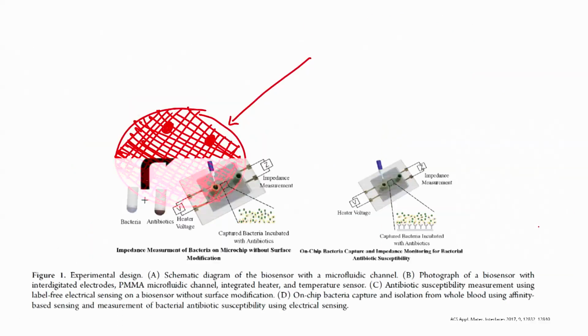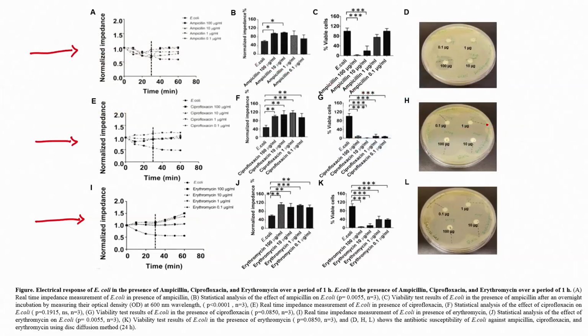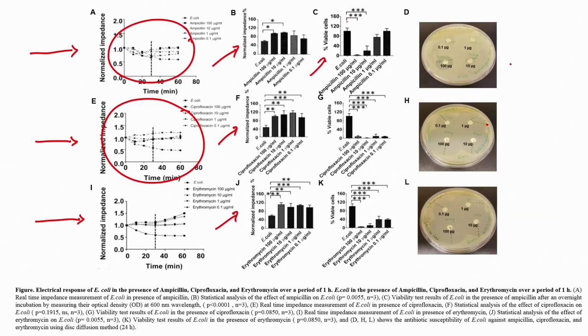antibiogram assay, correct. So, the antibiogram assay you can see here for different concentrations, 0.1 microgram to 200 microgram in all 3 cases, and this is our gold standard. We are comparing the results with our gold standard. We have also done the viable cell studies, and whatever impedance values we get here, we have normalized it with this, and this is a normalized impedance plotted for E. coli, which is our control sample, and then the E. coli captured with ampicillin of different concentration, and we can see the effect of antibiotics by looking at the impedance change. And we can also correlate it with viable cells here, that this is statistically different. The ampicillin 100 microgram is statistically different, 10 microgram is also statistically different compared to the control, while 0.1 microgram and 1 microgram is not different compared to the control, right.